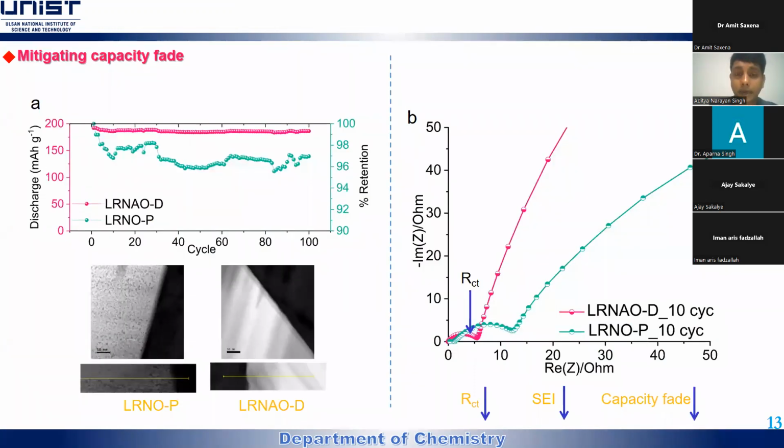Again, the capacity decay, as I mentioned earlier, is more or less directly related to the integrity of the crystal structure, of the grain boundaries or grains. So we took the cycled images under HRTEM. And what we found, interestingly, is that aluminum dope has an intact crystal structure even after long cycling, after 100 cycles. But we see in nickel dope, there are some pits on the surface structure. These pits are corrosion, because in the presence of electrolyte, HF can corrode this.